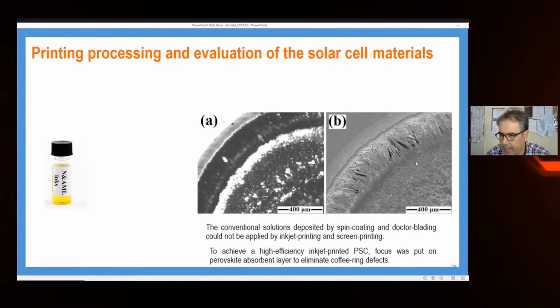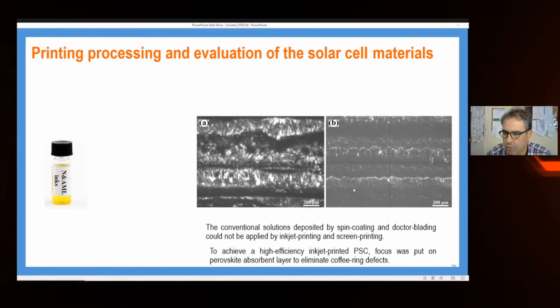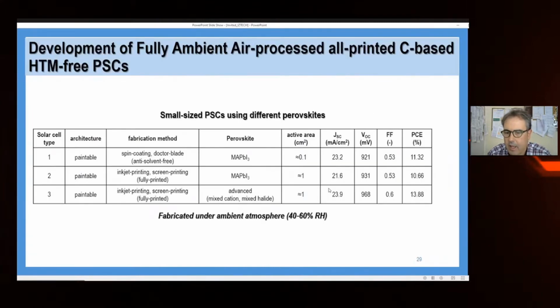This is the coffee ring effect as referred to before. The crystalline phase here is different from the other. So we have to be very careful about the material that we use and the method to apply on the substrate. These are some images, again, to expose the problem of the coffee ring effect.